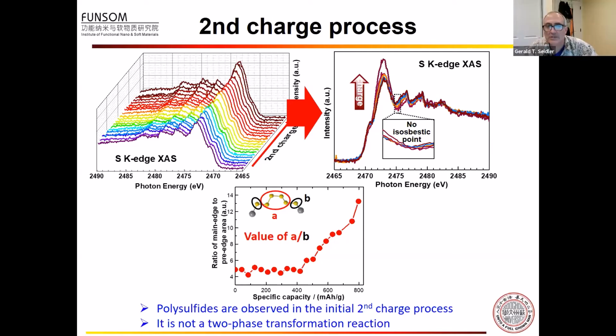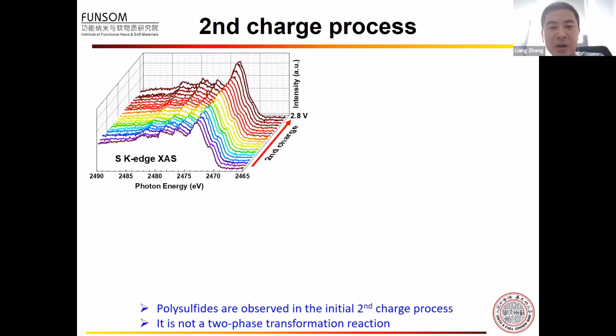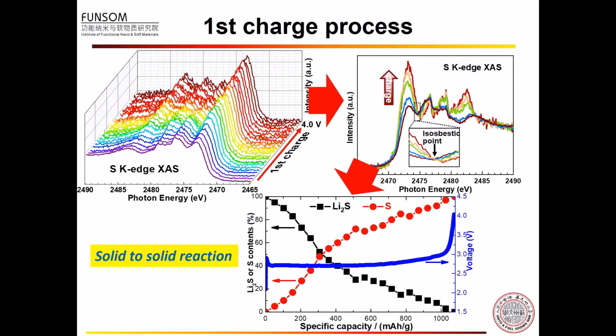Okay, very good. Kevin, you have a question? Yeah, hi, Liang. Really nice. This is Kevin Rosso. I'm curious about the Li2S crystal structure possibilities versus an amorphous structure, and if you've evaluated this difference, and if you get a battery voltage difference associated with the structure difference, I would suspect you would. Actually, for the initial lithium sulfide, we measured the XRD. It has a crystal structure. But after cycling, we also measured the Li2S sample, and all the diffraction peaks disappear. It seems it becomes too amorphous even after only one cycle. So we don't know the reason for that.